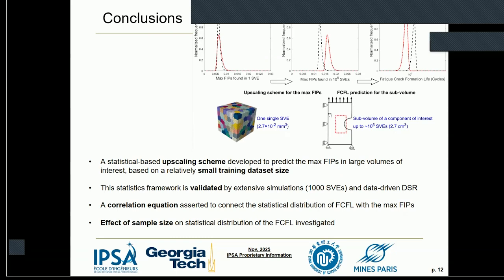So we developed one statistical-based upscaling scheme. We just use a smaller volume and we can predict the fatigue lifetime in a much larger volume. This statistical framework is validated by extensive simulations and also data-driven DSR. We also introduce correlation equations to link the fatigue crack formation lifetime with the maximum value of the FIPs. In this way, the effect of the sample size is accounted for. We also discuss the texture effect on the fatigue lifetime as well. That works also very well.